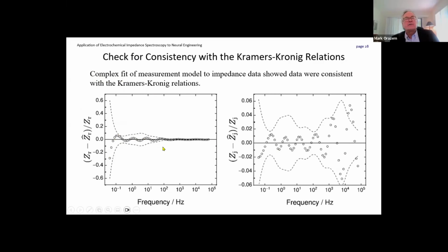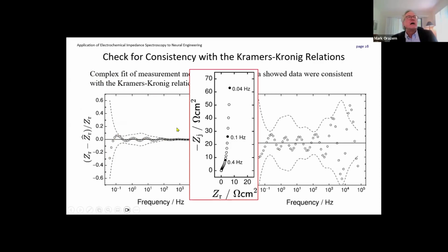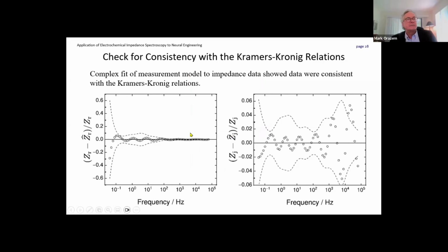Now, if any of you have followed my work, I used to like to say that I like to fit to the imaginary part to predict problems with the Kramers-Kronig relations at low frequency. I found that does not work well for data like this, where we get nowhere near the 0 frequency limit. So when we see data like this, a complex fit is what we need to use. And that's what we use for all the data.